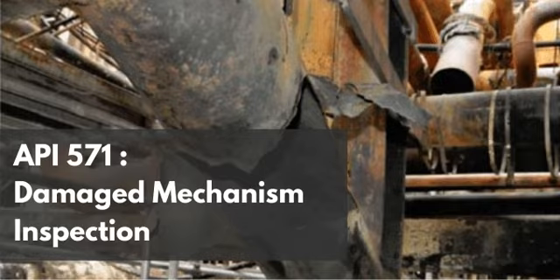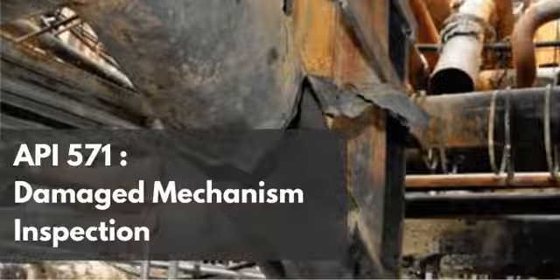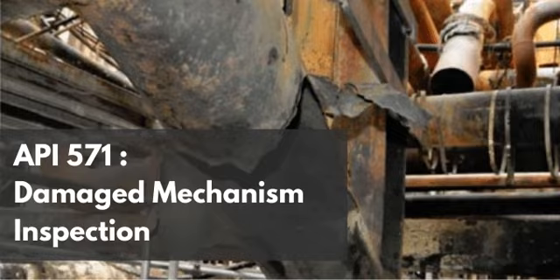Right, the tight packing. That specific atomic arrangement is stabilized by elements like nickel and, crucially, by the chromium dissolved in the solid solution. But remember what the invading carbon does. It diffuses in and specifically hunts down that chromium. It forcefully robs the matrix of the chromium to form those brittle chromium carbides. Right. The carbon steals the stabilizing shield.